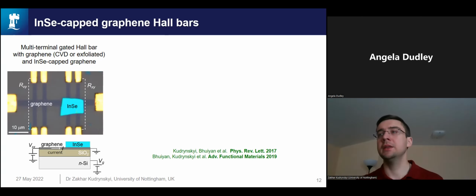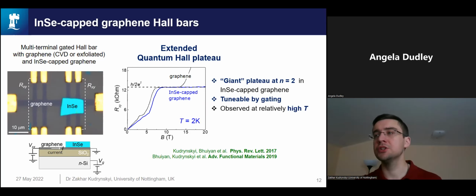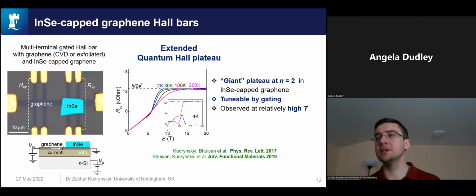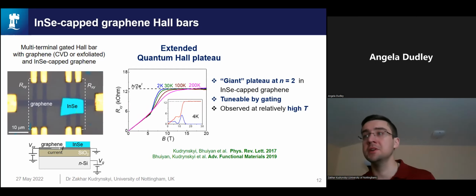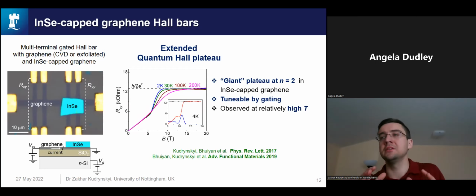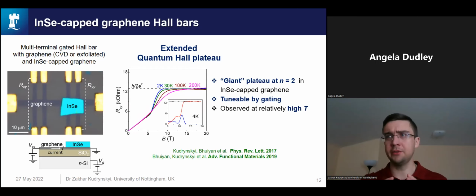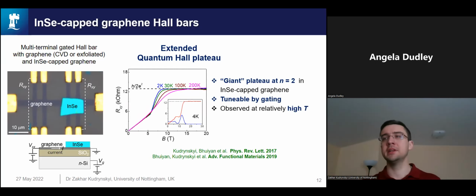So we did it, and what we noticed is that the two parts of the device tend to have distinct behavior. In one case, where the graphene is capped with InSe, we see this large quantum Hall plateau. This is at low temperature and extends from a few Tesla up to 20 Tesla. Later on, we extended these measurements to high field, to 30 Tesla, and the plateau is still there. But it is also quite robust. It is observed nicely up to temperatures of the order of 200 Kelvin.